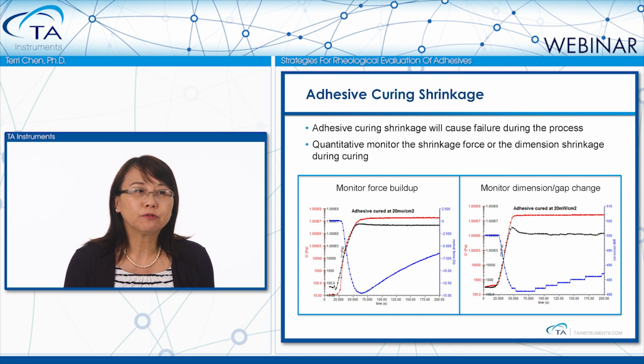If we actively release this shrinking force to 0 during curing, then we can monitor the sample dimension change. The blue curve on the right side of this figure shows how much the gap reduced during curing.